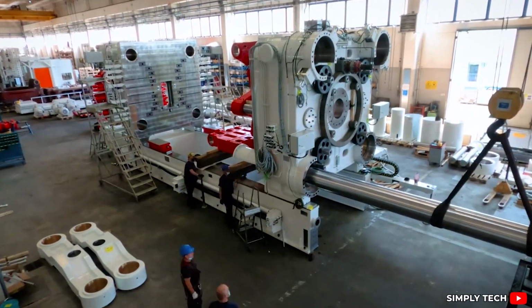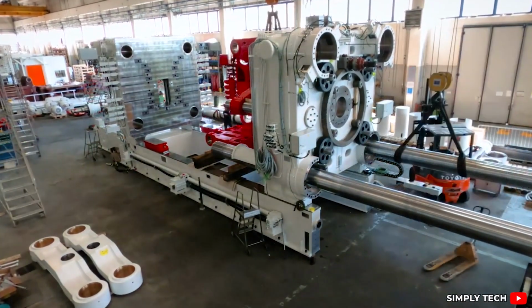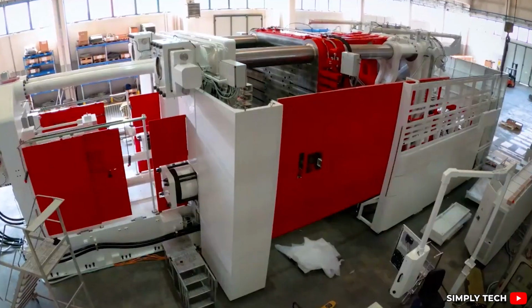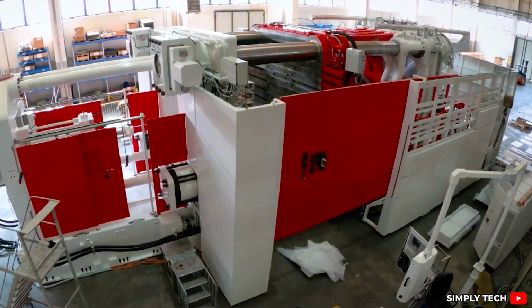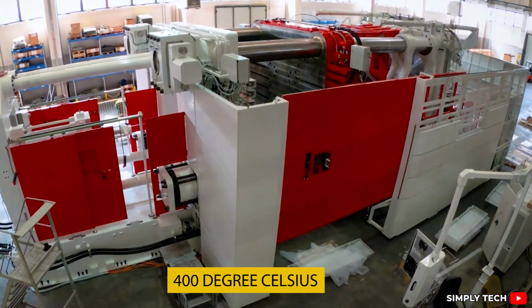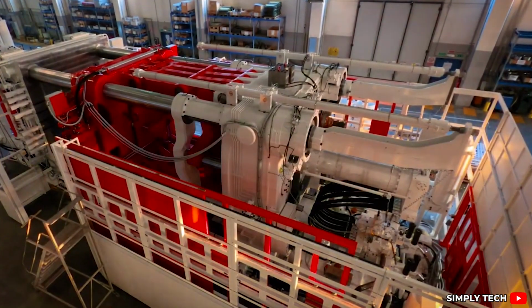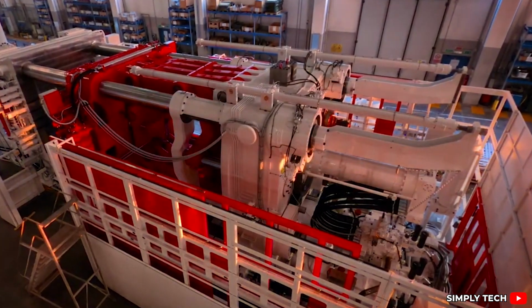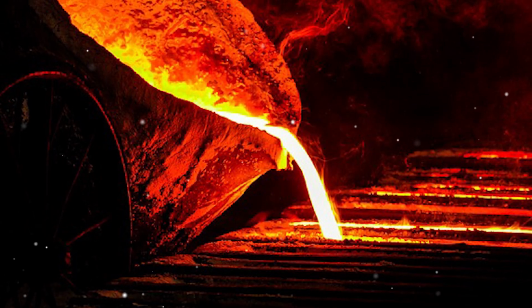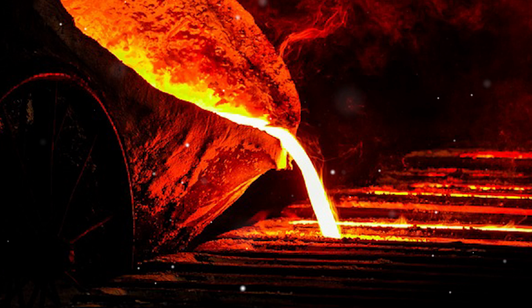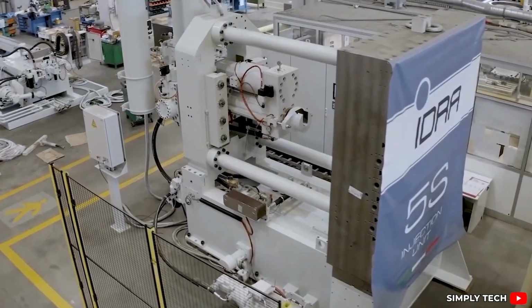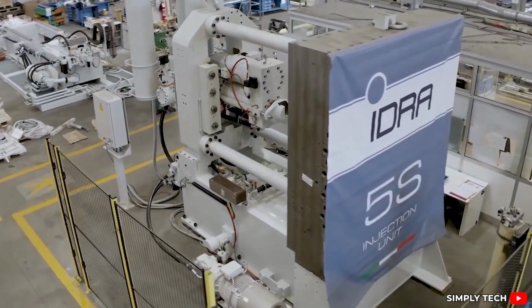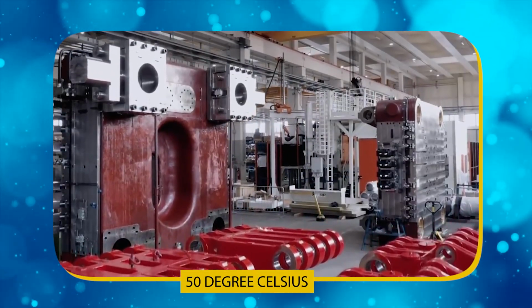The casting cools inside the mold until it hardens enough to hold its shape. Then it's ejected while still glowing at around 400 degrees Celsius. Yes, 400 degrees. And that's when the real cooling begins. The raw, red-hot casting is immediately placed into a cooling bath. Here, its temperature drops drastically, from 400 degrees Celsius all the way down to about 50 degrees Celsius.